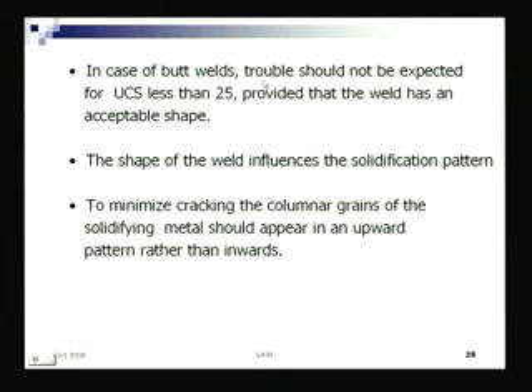So what we see is that in case of butt welds, trouble should not be expected for UCS less than 25. These are some of the thumb rules. If you have within say 25, then for butt welding it should not crack, should not develop. The shape of the weld influences the solidification pattern.